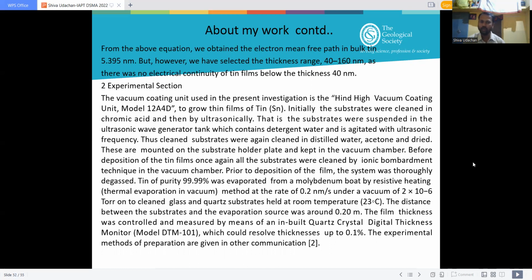The vacuum coating unit used in the present investigation is the high vacuum coating unit model 12A4D to grow thin films of tin. Initially, the substrates were cleaned in chromic acid and then ultrasonically. That is, the substrates were suspended in the ultrasonic tank, which contains detergent water and is agitated with ultrasonic frequency. Thus, clean substrates were again cleaned in distilled water, acetone, and dried. These are mounted on the substrate holder plate and kept in the vacuum chamber.